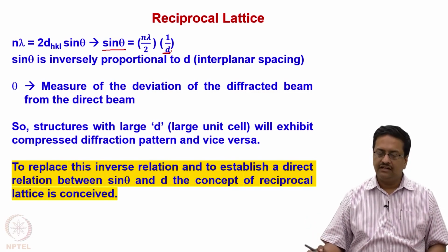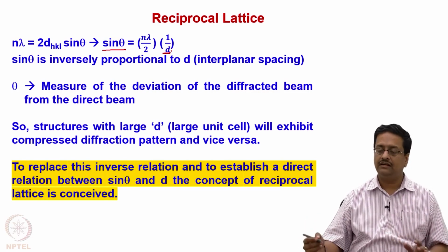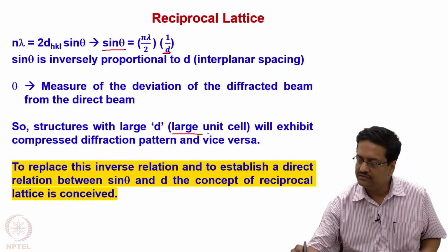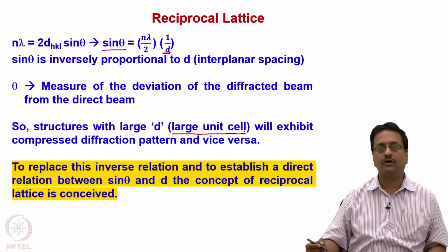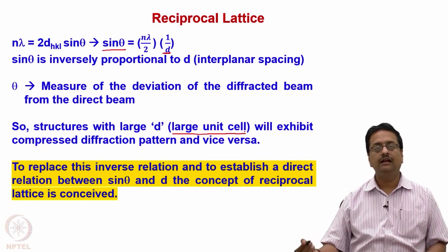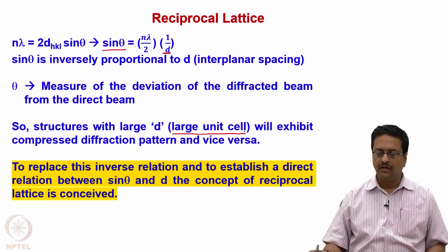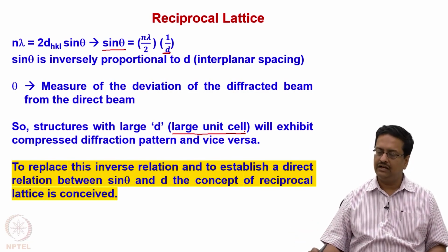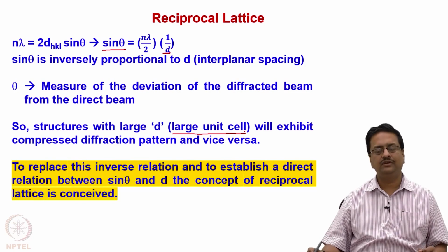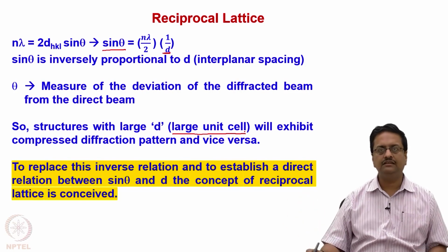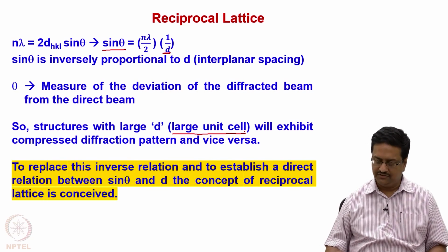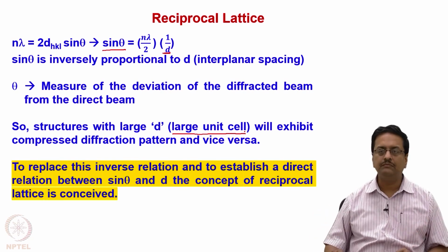Because of this inverse relation, the structures with large d, that means structures with large unit cells, will exhibit compressed diffraction pattern and vice versa. So to replace this inverse relationship and to establish a direct relation between sin theta and d, the concept of reciprocal lattice is conceived. Let us see what do we mean by a reciprocal lattice.